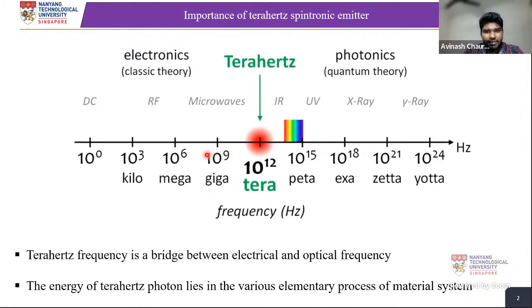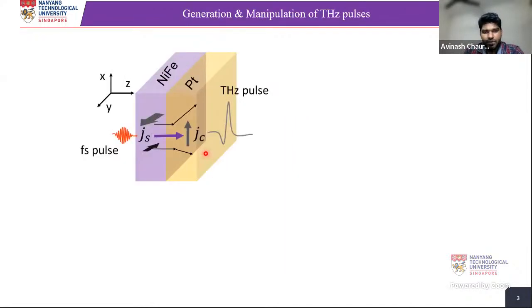So how can we generate terahertz spin current pulses? Basically, in a typical spintronic emitter, we have a ferromagnet and heavy metal interface. When we shine a femtosecond pulse on this heavy metal ferromagnet interface, we excite the ferromagnet, and due to this there is ultrafast demagnetization and superdiffusion of spins. So there is an injection of spin current from the ferromagnet to the heavy metal, which leads to the inverse spin Hall effect in the heavy metal, and we get a charge current.